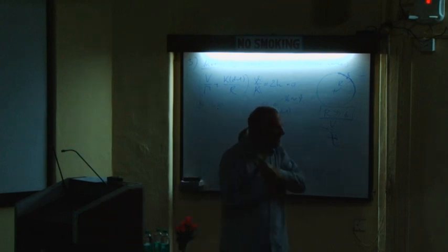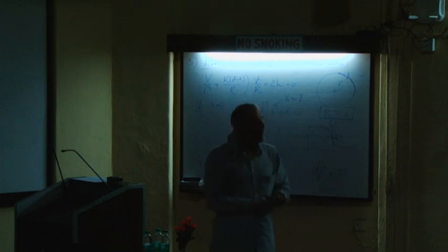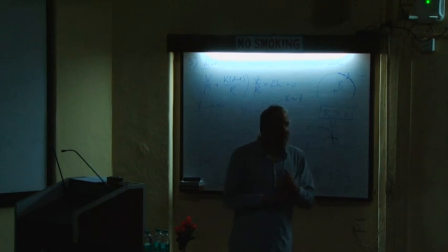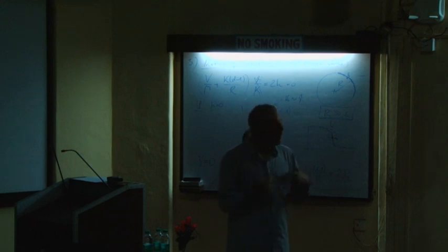First, if you apply a driving force, which here I applied under the form of a magnetic field, the interfaces will move, and they will move with a velocity that is proportional to the driving force. Okay? And this relation can serve to fix the kinetic parameters of the phase field model. And second, if you have a curved domain boundary, there will be a driving force exerted by the curvature, which will have a tendency for the system to reduce its surface area. And if there is no counterbalancing force, this will lead to motion by curvature.